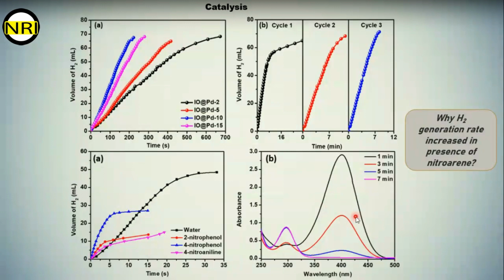So here it took only 7 minutes to complete this reaction, and we have calculated that this reaction follows pseudo-first-order kinetics. That graph I have not shown here. And one more thing, we have calculated that the rate of the nitrophenol reduction is faster than the hydrogen generation reaction.